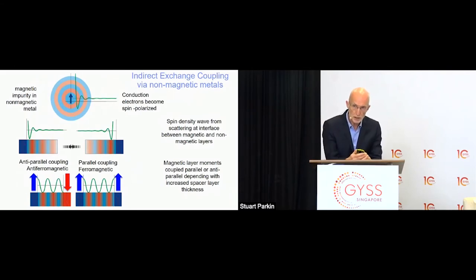So as shown in the bottom part of this foil, if you imagine two magnetic films shown here as blue and red, separated by copper, the spin polarization in the copper has a period of its polarization oscillatory behavior, which is reflective of the electronic structure and cannot be changed. So depending upon the separation of these two magnetic layers, the second magnetic layer will either see a spin polarization of the electron gas which is in the same direction as the first magnetic layer, or in the opposite direction. And this leads to an oscillatory long-range exchange coupling between these magnetic layers, which is useful for spin engineering interesting structures in superlattices. And again, this is something that I was the first to show and demonstrate.